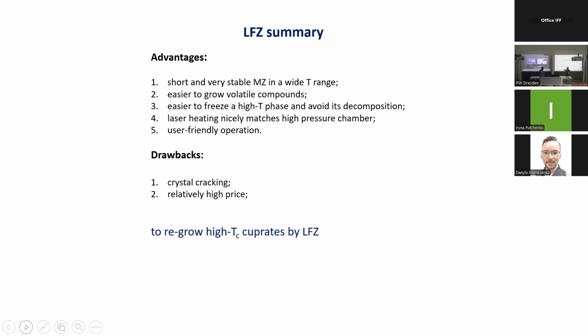It's interesting for me that it's possible to do annealing, pre-melting annealing, with an optical furnace. I thought that you always should do it in some separate furnace. No, first you do it in a separate furnace, but then you use this feed rod for pre-melting, and you densify. For this purpose, you need an image furnace, and you can control it. You just see by eye how it becomes narrower. When you go up with some heating zone, you do not have this melting region, you just have a heating zone.